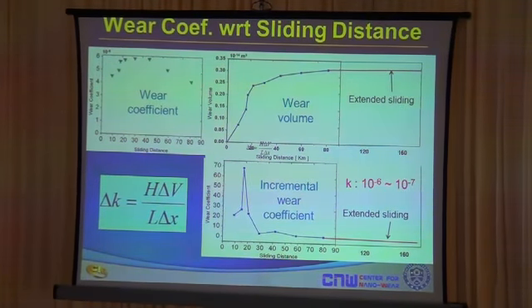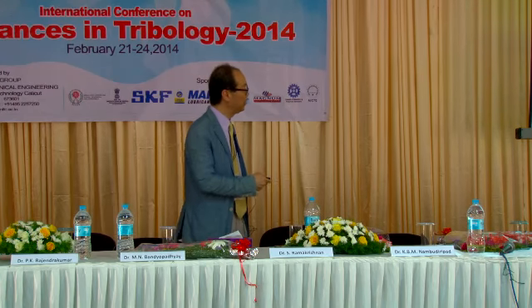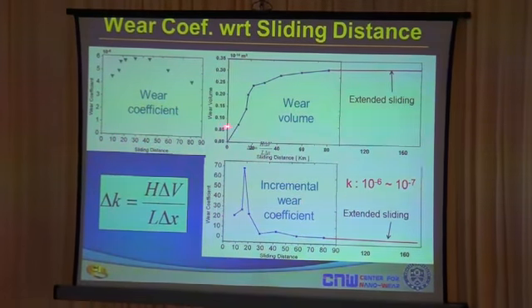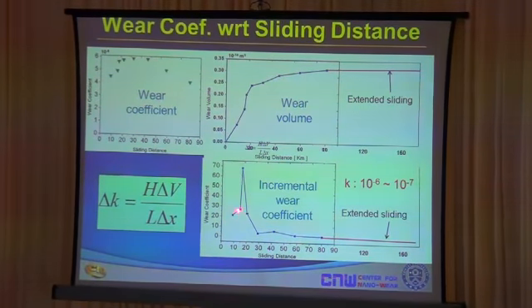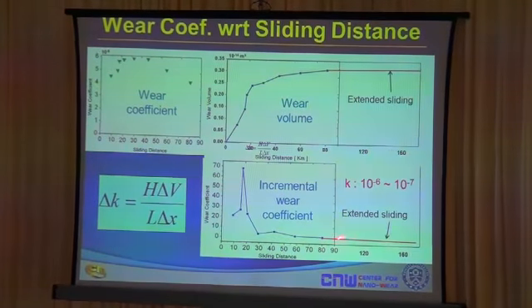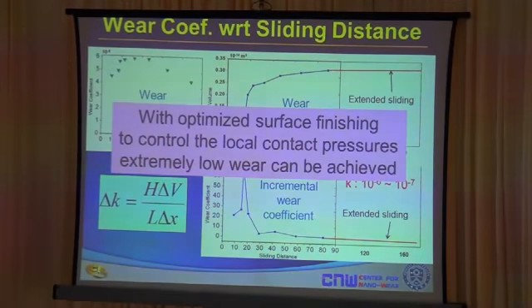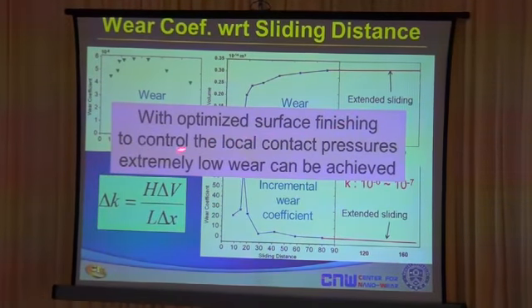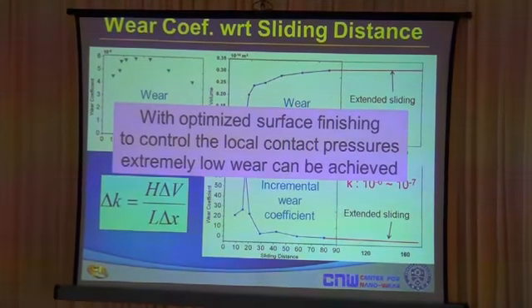Now, from this, what we do is that we measure the incremental wear coefficient, the wear coefficient between sliding distances. The incremental wear coefficient is defined by this particular equation. So between sliding distances, if we measure the incremental wear coefficient, it goes up and it goes down to a very low level. And with extended sliding, basically what we're saying is that we can eliminate wear to a great extent. As the material runs in against each other and optimizes the sliding interface, you can see that the wear decreases tremendously. And we can use this concept actually to design the surface to start with. In other words, with optimized sliding, with optimized surface finishing, we can control the local contact pressures to achieve extremely low wear. And if we can do this with machines that we're using for automobile component parts and all that, I think we can reduce the initial phase at which we initially have high wear.